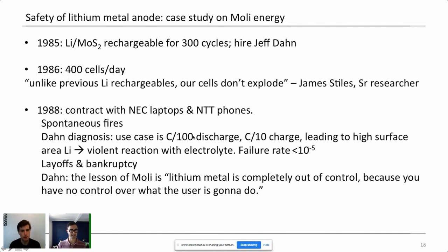C by 100 means a 100-hour discharge, but a 10-hour charge. And that led to a high surface area lithium, this coral or dendritic-like lithium that I've described, which would cause a violent reaction with the electrolyte. So their failure rate was only something like 10 ppm. However, it was enough that the company went out of business.